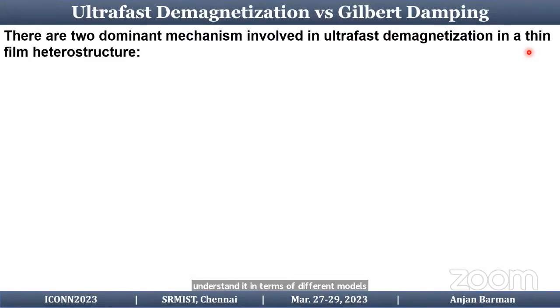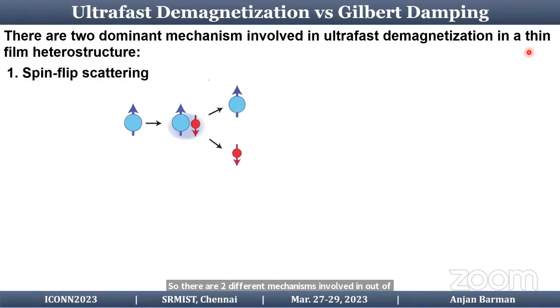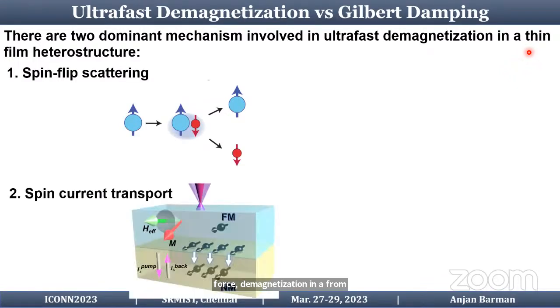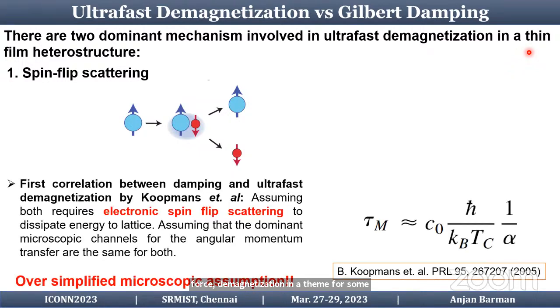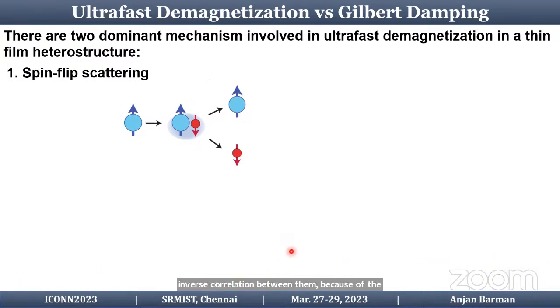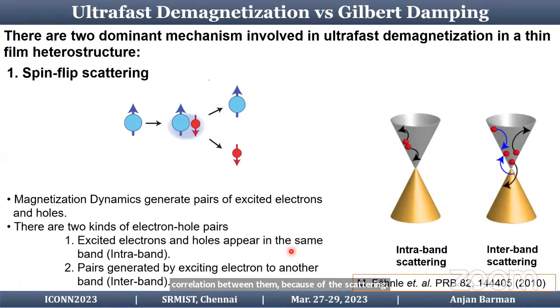So there are two different mechanisms involved in ultrafast demagnetization in a thin film heterostructure. One is spin flip scattering, the other is spin current transport. And in 2005, Koopmans gave a theory which shows that there can be an inverse correlation between them because of the spin flip scattering, but that was an oversimplified approach. Then in 2010, another model comes with interband and intraband spin flip scattering, electron hole pair generation and scattering.